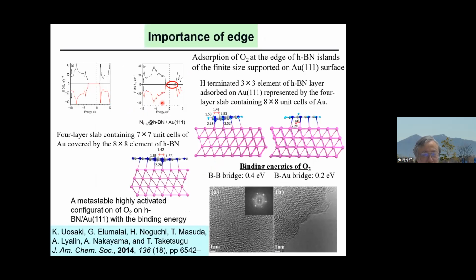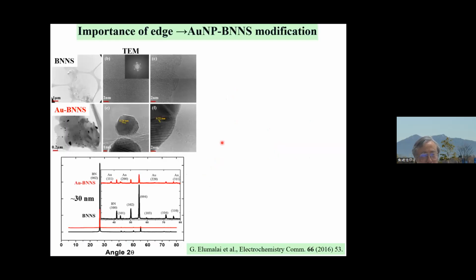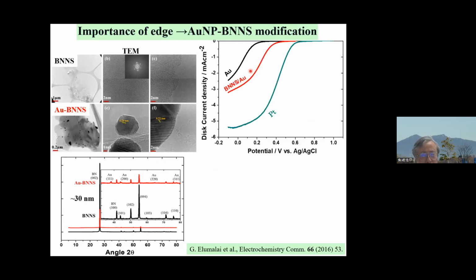Then we carried out various other calculations, using small boron nitride and so on, and we found theoretically that the interaction at the edge of boron nitride with gold is very important. So we added gold nanoparticles on top of boron nitride so that the interaction will increase. This is the result. This is the gold, boron nitride nanosheet gold modification. Then on top, we added gold nanoparticles. It became better. Not only was the potential shifted positively, but the limiting current also increased, which means a subroute of oxygen reduction to water is open.